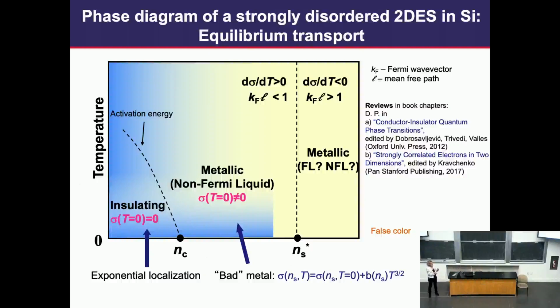In this case, conductivity is small. It has this peculiar so-called non-Fermi liquid temperature dependence, meaning it cannot be described by the standard quasi-particle picture. So we have a transition from an insulator to this kind of bad metal, or bad conductor.